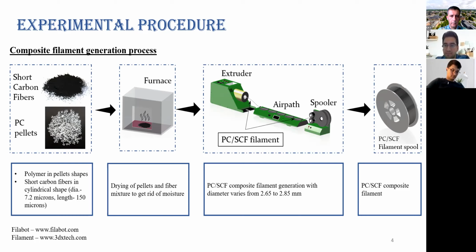Why are we drying these materials? That is the question people generally ask. We dry these materials to get rid of the moisture. This is a very important step in any part production, because if moisture is present in the materials, it will eventually degrade the quality of the final part. So whatever material we are using, we have to dry it for 7 to 8 hours continuously, at a particular temperature below the melting point of the material we are using. So that's okay.